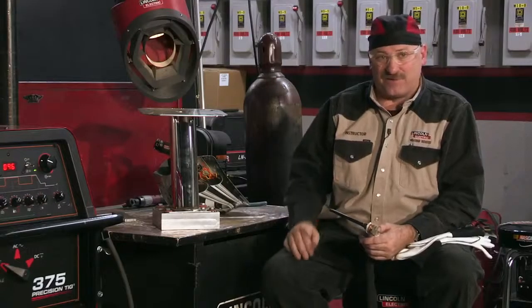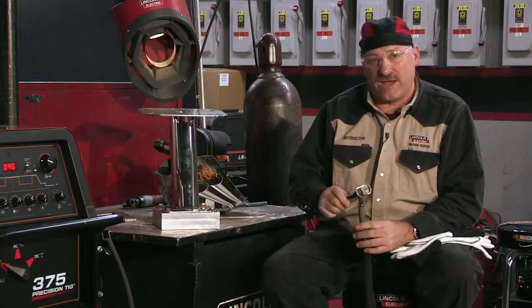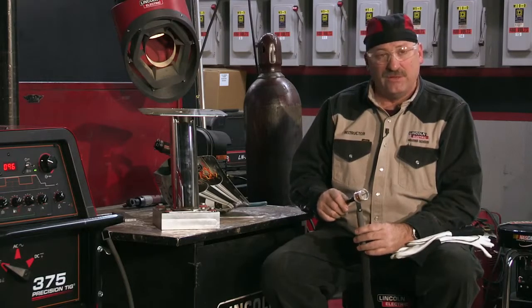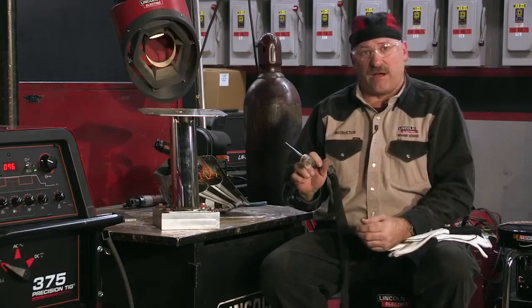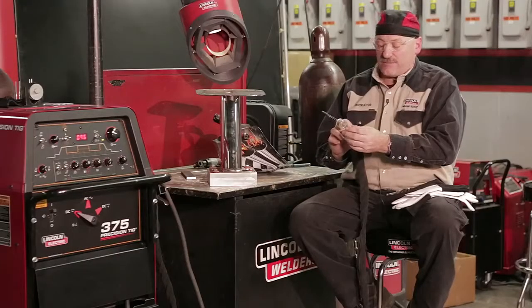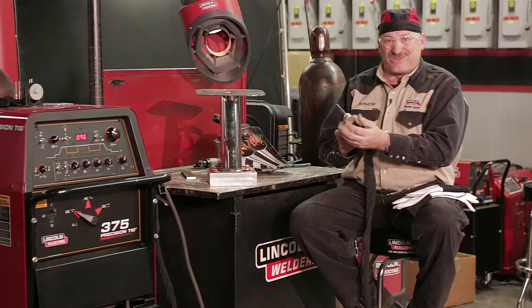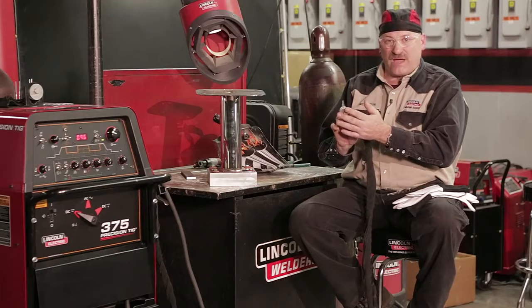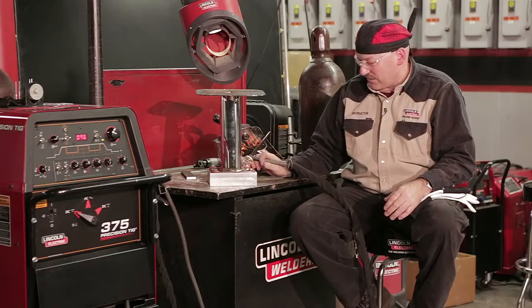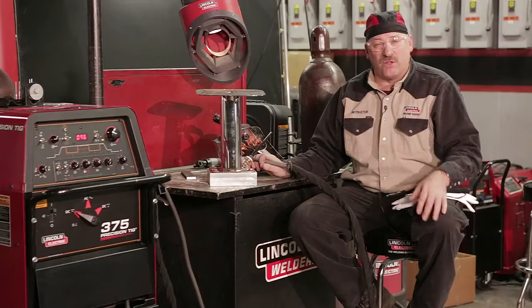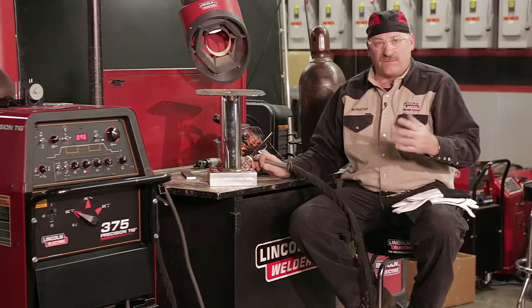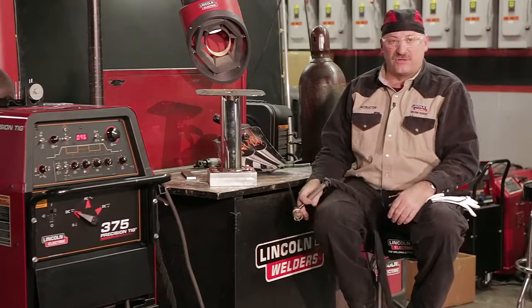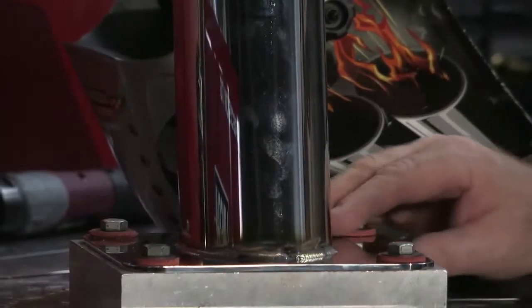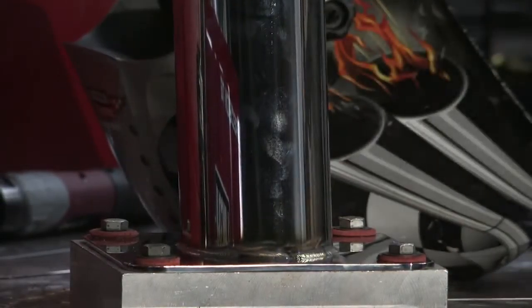I kept my amperage as low as possible, but I also kept my travel speed up as high as possible. I kept my voltage down by keeping my arc length close. Kept the arc length close by extending my tungsten beyond this Pyrex cup as far as possible. That allowed me to get in real close and move along as quickly as I could. The less heat input, the less distortion, less problems we're going to have with buffing afterwards. This should polish up real nice.